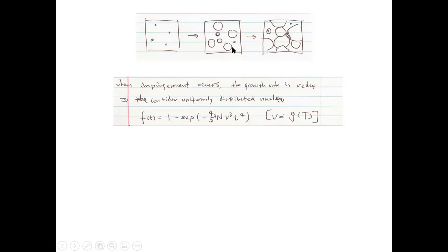We have to consider their interactions, all the other stuff. But eventually, you can still solve this problem, which is not very difficult. And the final solution for the cellular transformation scenario is this: if you want an overall picture of how the transformed fraction changes with time, you get this. So it's not a simple power law, it's an exponential function, and within this exponential, you have a power scaling.